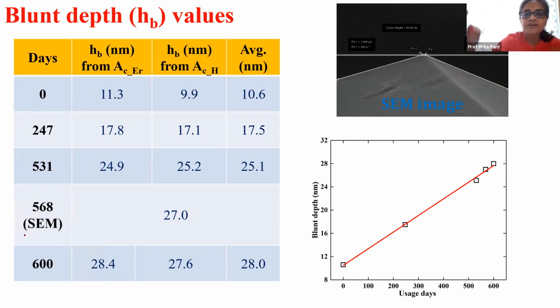Let me see whether it's going to let me write on this at all. Right? So we are assuming, I'm going to make a 2D drawing. I'm assuming my tip is like this. And I know the included angles, but you see my tip is not like this. And to take care of that, my tip is actually something like this. And Oliver and Pharr had proposed that, look, you take this 8th order polynomial and you fit to it, and it takes care of this blunting for you. And what we found is that that may not be working. So we have estimated what we are calling the blunt depth, which is basically this depth.